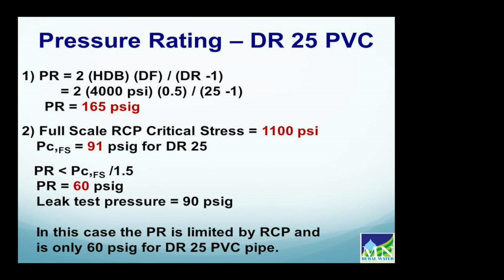Recall that for PVC pipe, based on Dr. Lieber's S4 critical pressure data and the ISO correlation equation, the full-scale critical pressure for DR25 pipe would be 91 psig. Again, that's based on the stress. Once we know the stress, we can determine the pressure for any DR, dimension ratio. So what that says from the equation is the critical pressure is 91 psig.